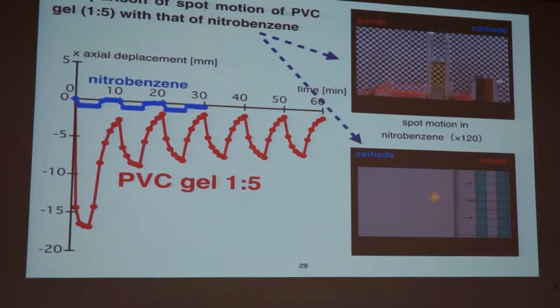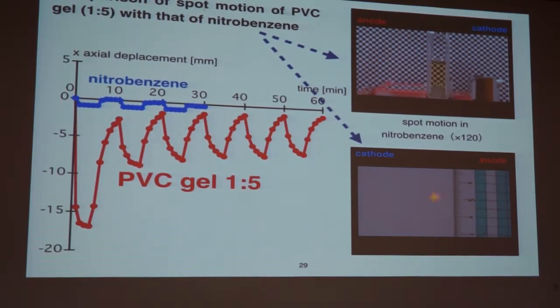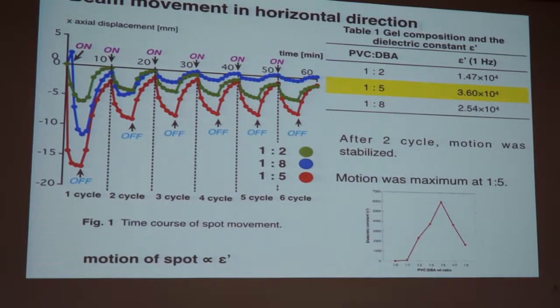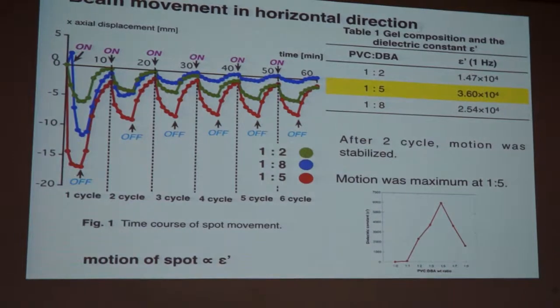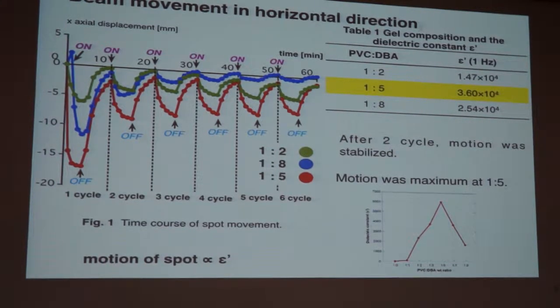And you can see it's very difficult to see a big change of the distortion of the image. So the diffraction is small. This is the case of the PVC gel, PVC transparent gel.